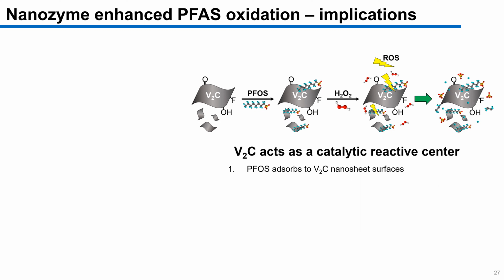due to the physical and chemical properties of the vanadium carbide, a two-dimensional nanosheet, so very, very high surface area. And it's also a carbonaceous nanosheet. And we know that graphene oxide, activated carbon are all very, very effective adsorbents for PFAS. So we think this is the first step of what's happening in our system.